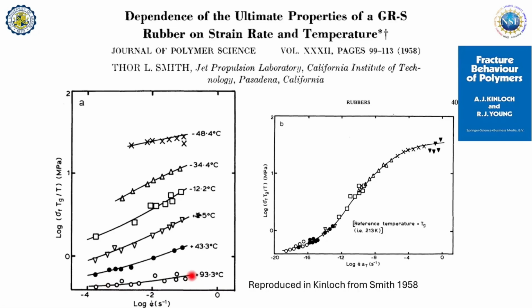Stretching at higher temperature, the resistance to rupture is lower. As you increase temperature, your rubber simply becomes weaker. But I do WLF, because lower temperature is equivalent to higher rate. So you get a master curve.